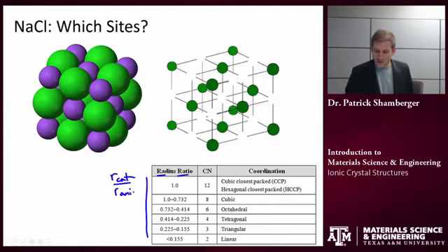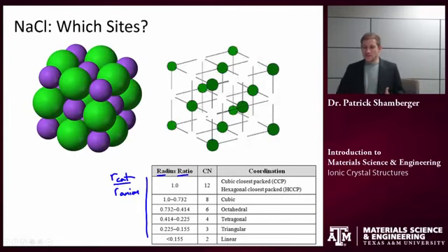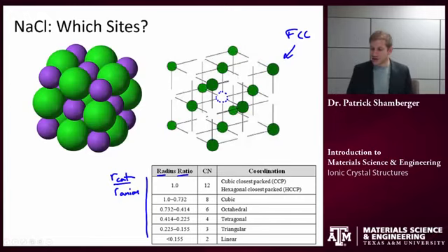And we can do this because we know that if we have an anion lattice, for example an FCC lattice, the available size of the different sites, for example the octahedral site right in the middle of the FCC lattice, I can calculate the size of that interstitial position as a function of the anion radius.